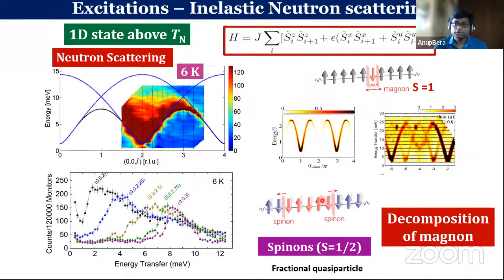These magnons are decomposing into 2 quasi-particles, and each of them carries spin half. And since there are 2 quasi-particles, and in a neutron inelastic scattering experiment we see the change of spin 1, we are basically seeing the combined effect of these 2 quasi-particles. So the combined effect gives us this continuum kind of behavior. This decomposition of the magnon is a purely quantum phenomenon, and these are fractional quasi-particles. They are of prime attention for quantum spin liquid systems.